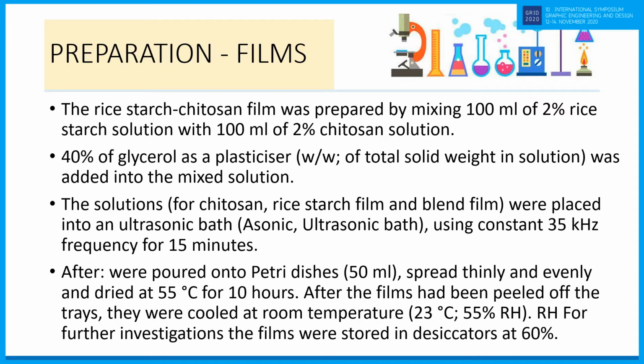The chitosan solution was prepared by dissolving 2 grams of chitosan in 100 milliliters of acetic acid, and glycerol was added as plasticizer. The solution was then mixed at 19 degrees Celsius for 5 minutes until the chitosan was completely dispersed, and then it was cooled to room temperature.